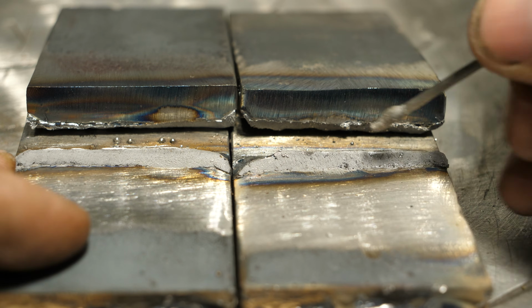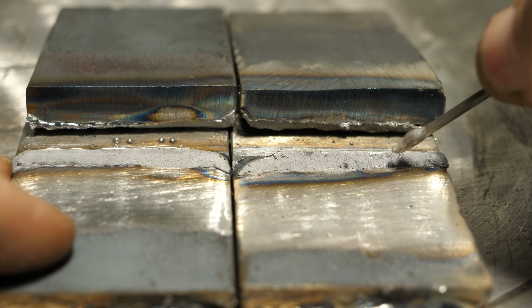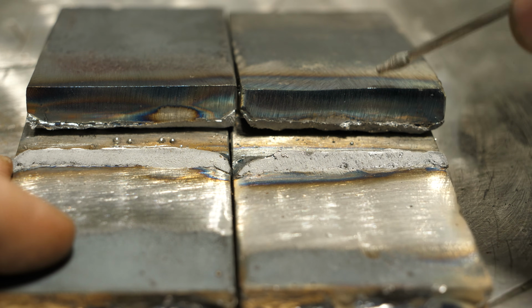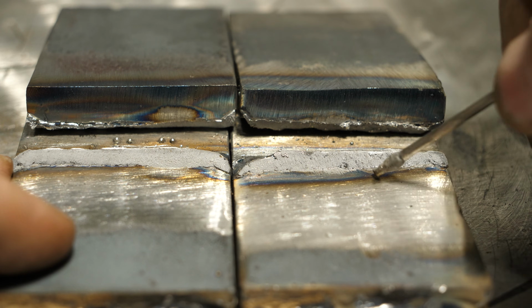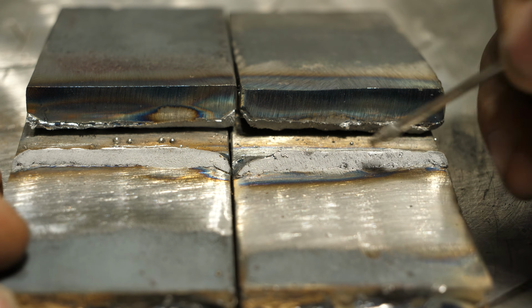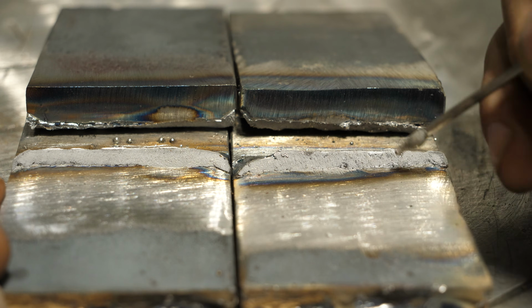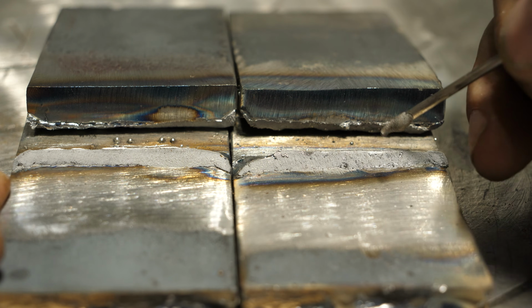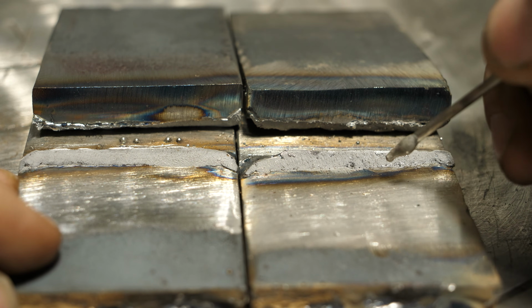Right away, this gray metal, that's our weld metal. The weld failed for the most part. It was not the plate. Most of it is the weld itself, which is what you want. If your weld peels off the plate, you got issues. So that's a good sign.